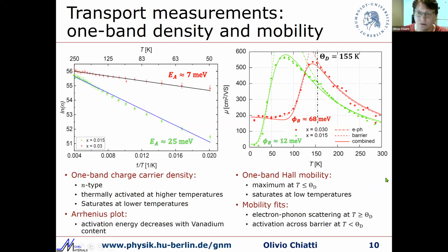We also performed some fits to get barrier heights, but how to interpret these numbers is not entirely clear yet. What we can say is that above the Debye temperature, we probably have bulk conduction that looks like electron-phonon scattering in semiconductors. At lower temperatures, it's a bit more complicated.